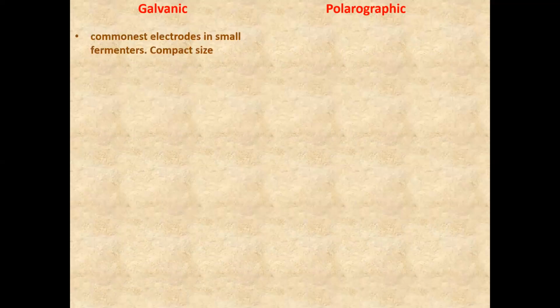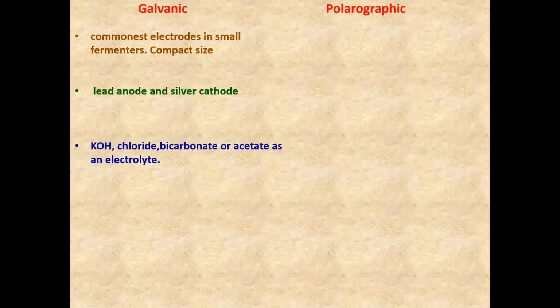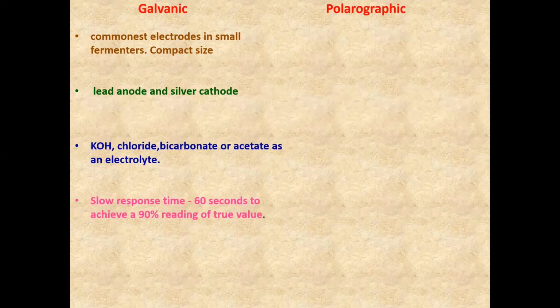In small fermenters up to 1 liter, that is the laboratory scale fermenters, galvanic electrodes are the commonest electrodes. They have a compact size. They have a lead anode and silver cathode and employ potassium hydroxide, chloride, bicarbonate, or acetate as an electrolyte. Now, the sensing tip of the electrode is made up of Teflon or polyethylene or polystyrene membrane, which allows passage of the gas phase so that an equilibrium is established between the gas phases inside and outside the electrode. Because of this, there's slow movement of oxygen across the electrode membrane. And because of the relatively slow movement of oxygen across the membrane, this type of electrode has a very slow response of the order of 60 seconds.